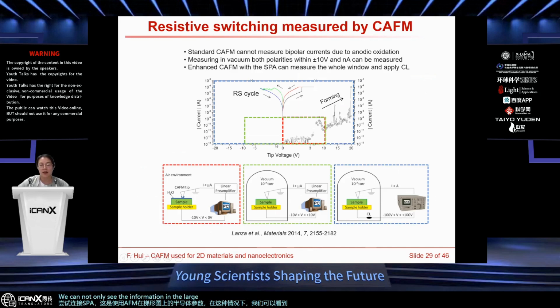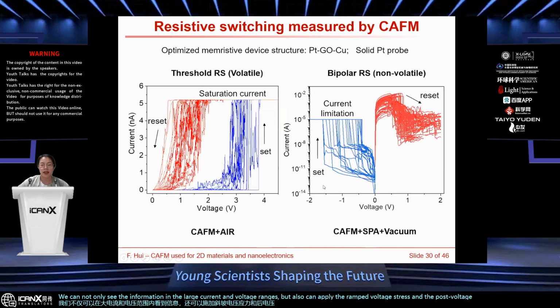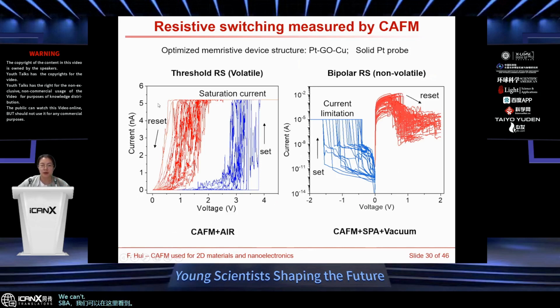In this case, we can not only see the information in the large current and voltage ranges, but also apply the ramped voltage stress and the pulse voltage stresses. Here I show one example collected by the standard C-AFM mode and by C-AFM plus SPA. We can only see current up to 5 nanoampere in the standard mode, but here we can get much higher current and larger voltage ranges.